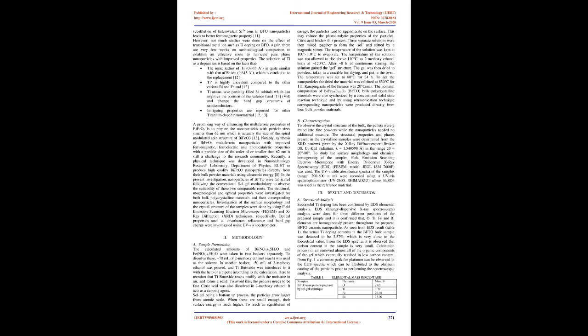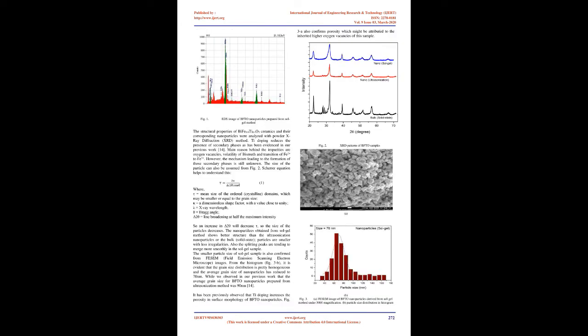A promising way of enhancing the multiferroic properties of BiFeO3 is to prepare the nanoparticles with particle sizes smaller than 62 nanometers, which is actually the size of the spiral modulated spin structure of BiFeO3 [13]. Notably, synthesis of BiFeO3 multiferroic nanoparticles with improved ferromagnetic, ferroelectric, and photocatalytic properties with a particle size of the order of or smaller than 62 nanometers is still a challenge to the research community. Recently, a physical technique was developed in the Nanotechnology Research Laboratory, Department of Physics, BUET, to produce high-quality BiFeO3 nanoparticles directly from their bulk powder materials using ultrasonic energy [8].